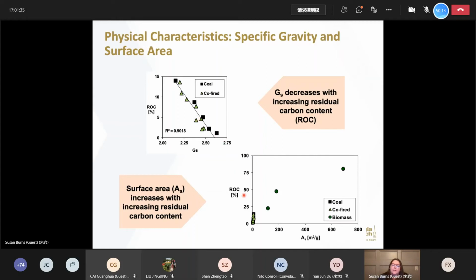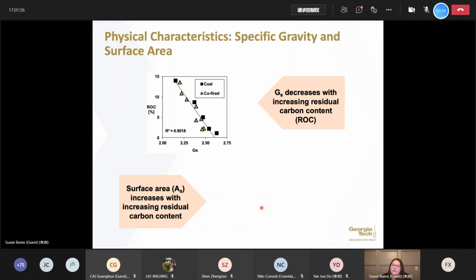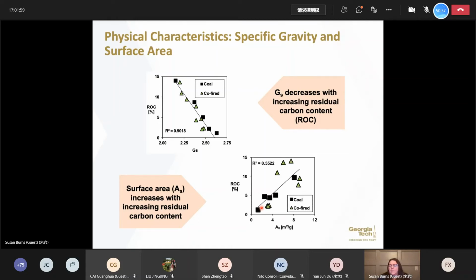What we see, though, when we look at surface area is slightly different. And so if we come in and take a look at our residual organic content plotted here on our vertical axis versus our surface area, what we'll see is that for these biomass ashes that we have tested, we get a much larger surface area as our residual organic carbon content increases. And we'll see that if we come down here and look at relatively low levels of residual organics, our surface area is not perfectly linear, but it's not too bad either, right? Not a great R squared, but it's somewhere in the ballpark.